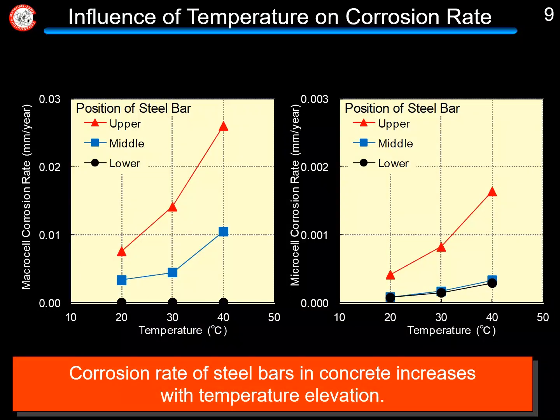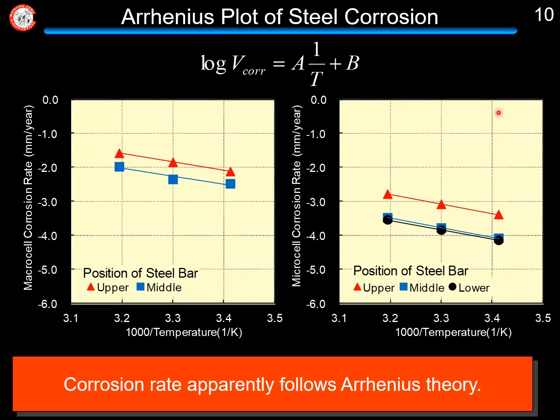This slide shows the temperature dependency of macrocell and microcell corrosion rate. From this graph, you can see that both corrosion rates of steel bar in concrete increase with temperature elevation. Additionally, the macrocell corrosion in concrete is relatively higher than that of microcell corrosion in those experimental cases. And those graphs show the Arrhenius plot of corrosion rate of steel bar in concrete. From those results, it can be said that both corrosion rates apparently follow Arrhenius theory.